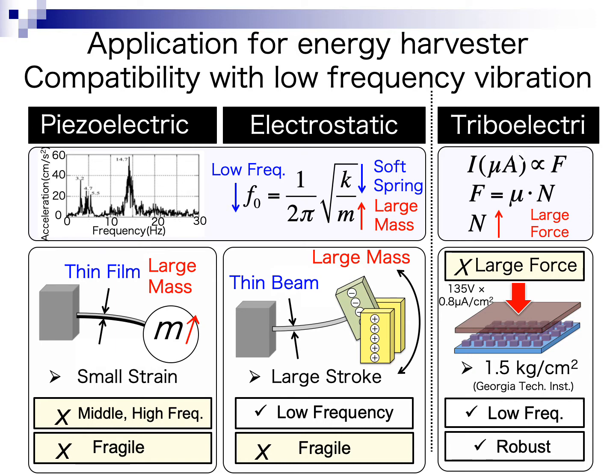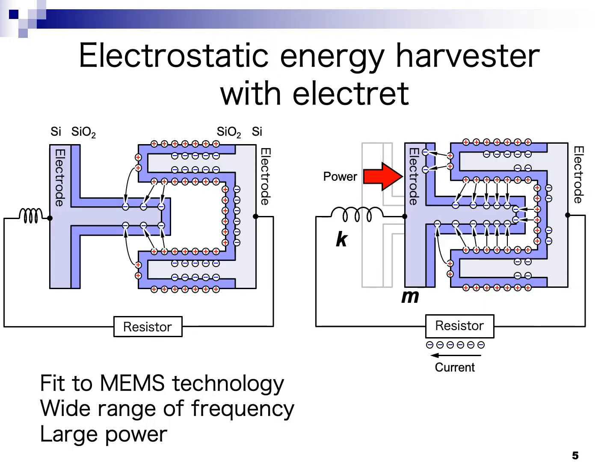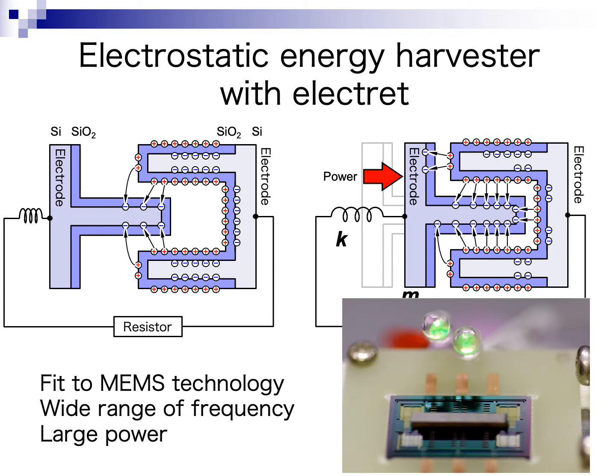To overcome these problems, in this work, we concentrated on the electrostatic energy harvester. This is a schematic picture of the electrostatic energy harvester with electret. If we insert an electrode to the electret, charges are induced at the electrode by the electrostatic effect. This method fits MEMS technology, and we can design the structure depending on the resonance frequency. However, there are still several areas to improve in these structures.